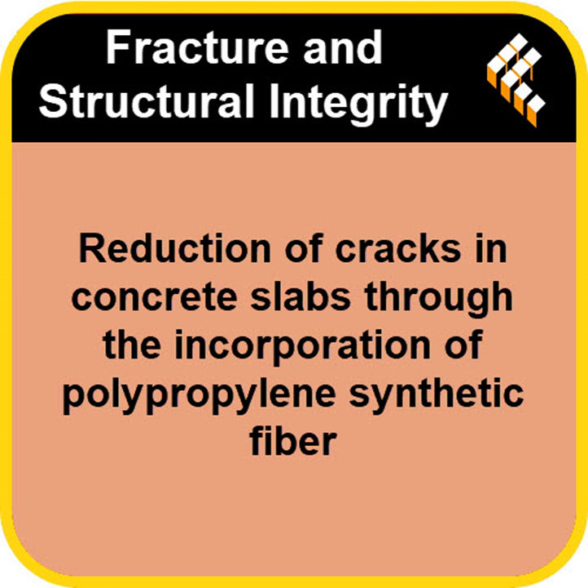Okay, so let's focus on that immediate impact. The first 4 hours, when the concrete is most vulnerable, this is the plastic state. Right. Here they used the C1579 test, as intended, comparing the control mix against their most promising dose, the DM02 at 1,000 grams. And they were measuring water evaporation. What did they find? The results were pretty striking. The control mix, the one with no fiber, it lost water at an alarming rate. We're talking 6.32 kilograms per square meter per hour over 4 hours.